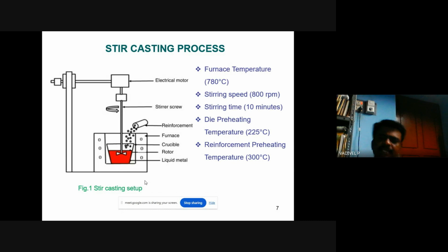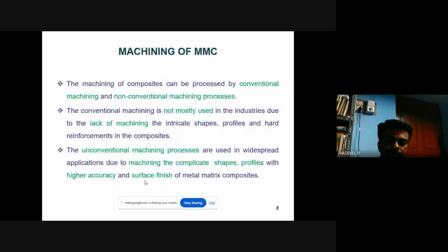The preheating of this reinforcement is required because the matrix is aluminum metal, and aluminum is softer, but the reinforcing ceramic is a very hard material. So the bonding will not be proper. To improve that bonding, we have to preheat the reinforcement material up to a particular temperature, and it should be maintained at the same temperature for a few minutes.